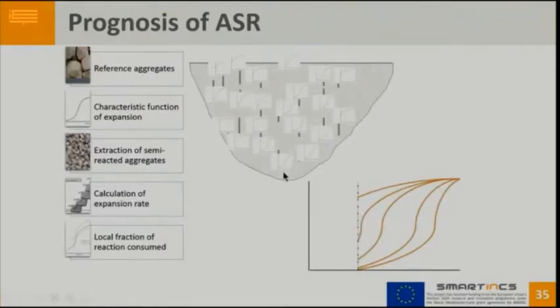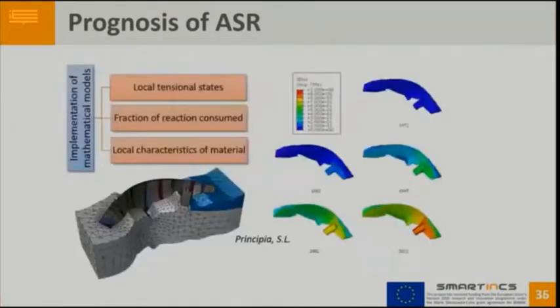And in this case, we can produce a mixed model that takes into account the fraction of reaction consumed, the local tensional states, and the characteristics of the materials, for instance, tensile strength.